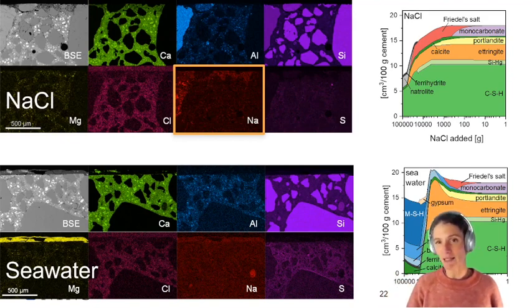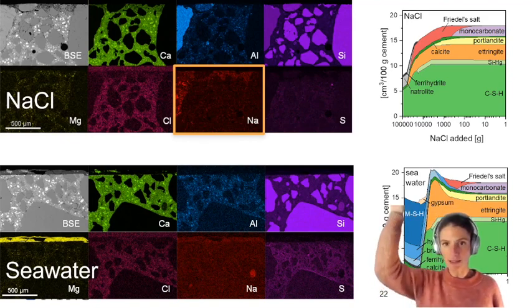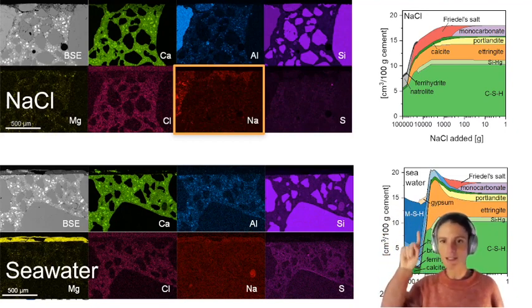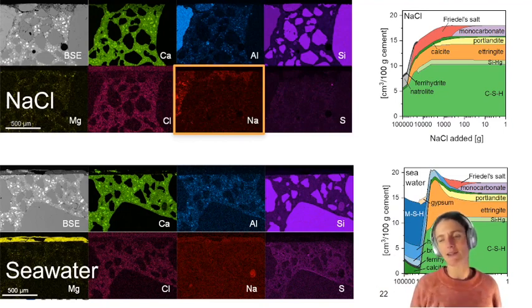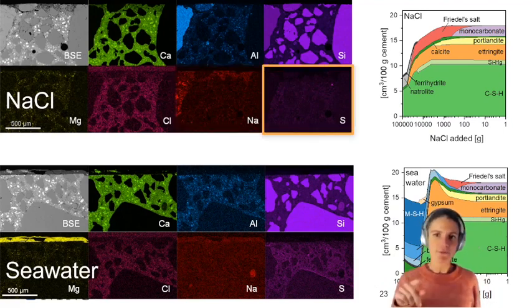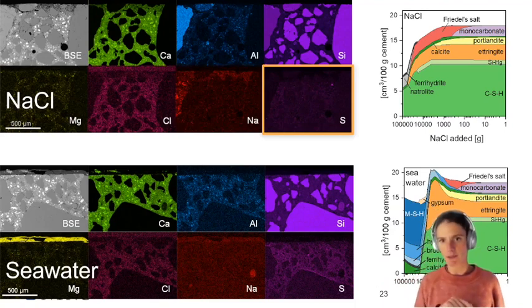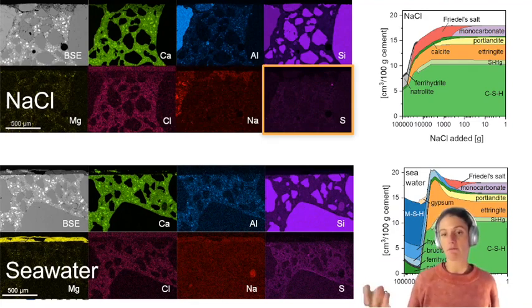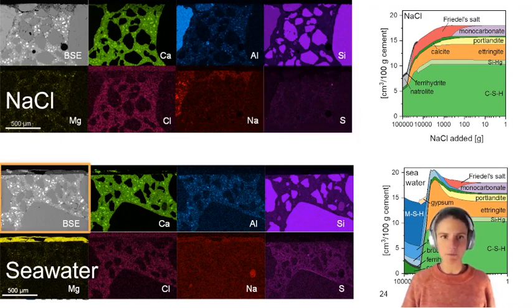And that might actually match if we look at the modeling on top here. I think it doesn't reach that part, but there you can see natrolite. And the sodium might be an indication of zeolite precursors forming at the surface. For sulfur, then there's also not that much to see. So these findings from our elemental maps and our BSE image indicate that we have leaching towards the surface and we have chloride enrichment in the paste, which matches our model. So that was nice. But let's now look at the seawater.